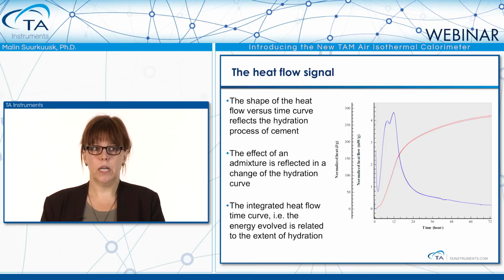The heat flow signal can look like this. The shape of the heat flow versus time will reflect the different processes of the hydration of the cement. And an effect of an admixture that's added to a cement or concrete will then be reflected in a change in the hydration curve. The integrated heat flow curve is the energy evolved and is related to the extent of the reaction. In this plot, the blue one is the heat flow curve, where we can see the different processes going on, and the red ones are actually duplicate samples of these. The two red curves are the total heat that is produced over time.